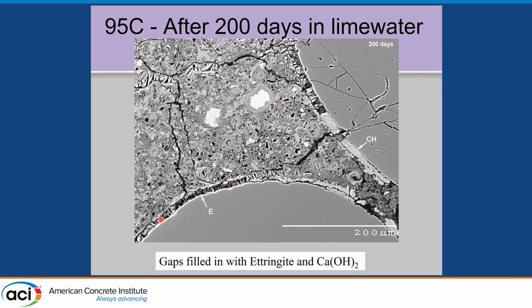So you see ettringite here in the lower left, marked by an E, where ettringite is formed in those gaps. Some places calcium hydroxide has also done the same thing and filled in those gaps. So the gaps were not initially filled. The gaps were empty because of the swelling of the paste, and then the ettringite filled in those spaces due to Ostwald ripening, moving small crystals in confined spaces into open areas where there's less energy.